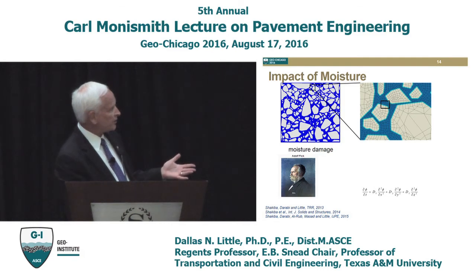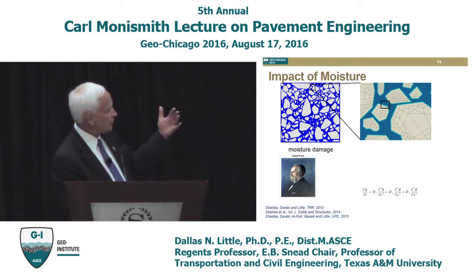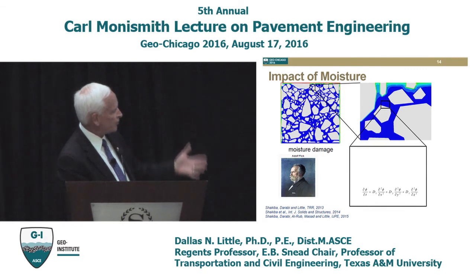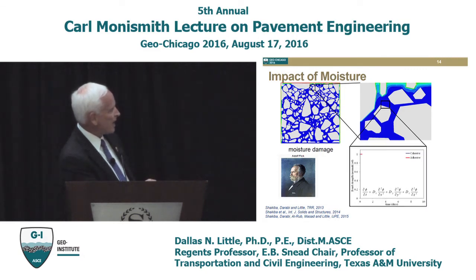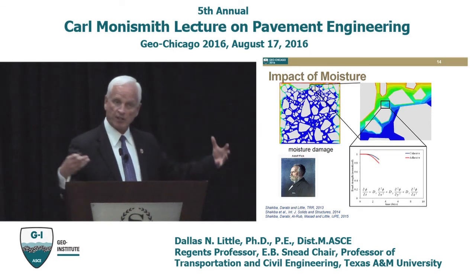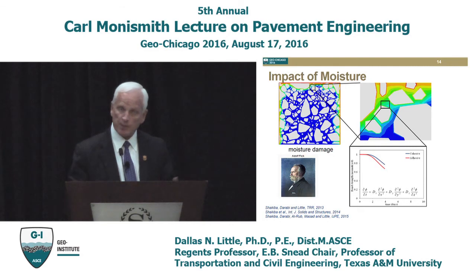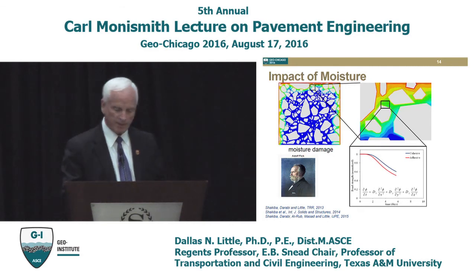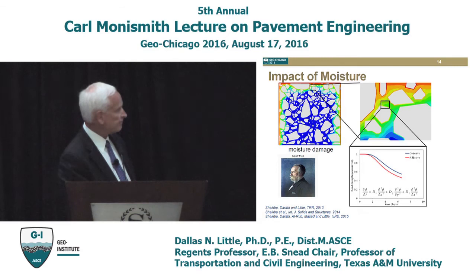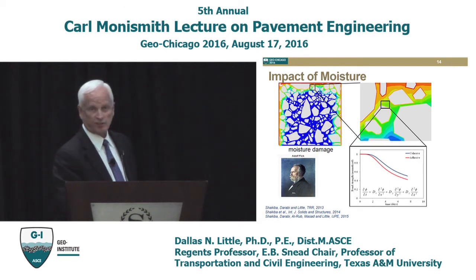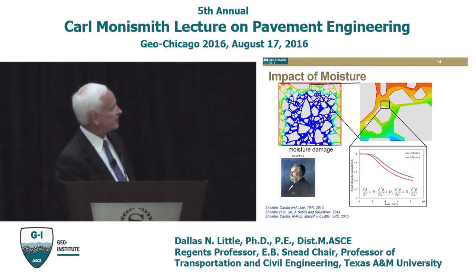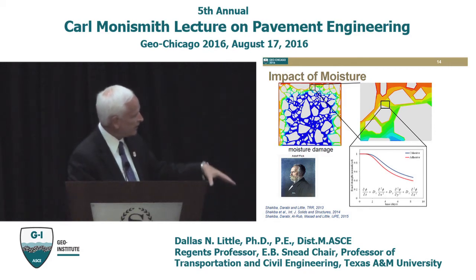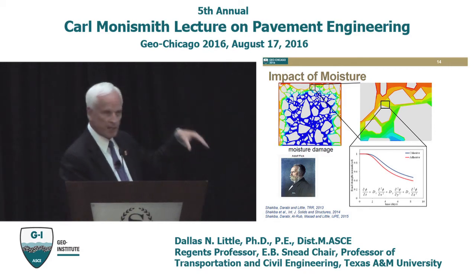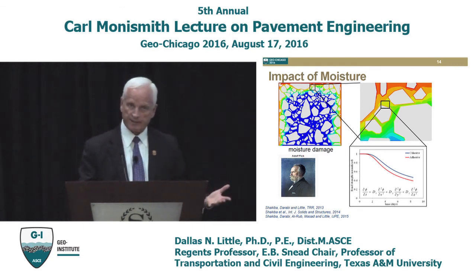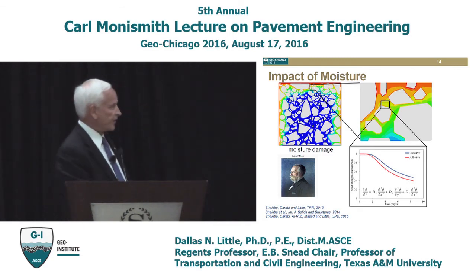Now, in this particular simulation, what you're seeing is that moisture diffuses, and as moisture diffuses, we're tracking the bond strength. The blue is the cohesive bond strength, or the strength of the mastic that's now being compromised because it's moisture laden. And the red is the strength at the interface, the adhesive strength at the interface. And you can see that they diminish as moisture increases into the sample as the moisture state becomes higher and higher. Now let's go a step further.